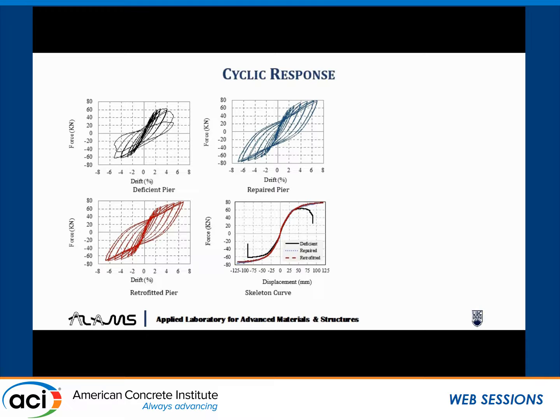So this was the repaired specimen, and this was the retrofitted specimen. And what we observed is that both specimens performed almost very similarly. Although this one was repaired, and although the bar buckled and everything, we did not do much. We just put in some additional stirrups, because some of the rebar stirrups were actually fractured. So we added some rebars, and the bent bars we pushed back inside, right? And then we put in the concrete patching and GFRP repairing, and then they were performing very similarly.